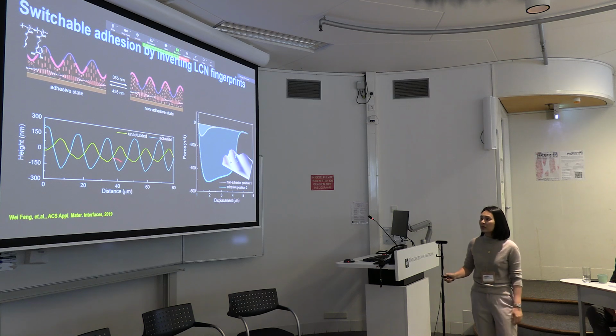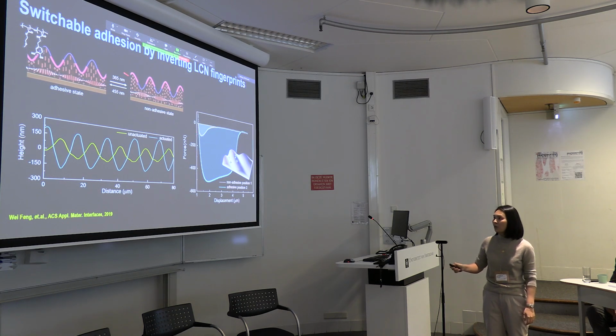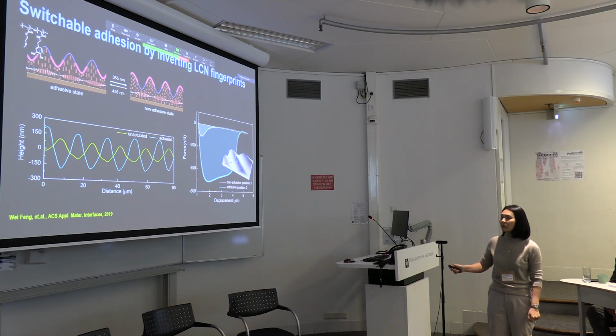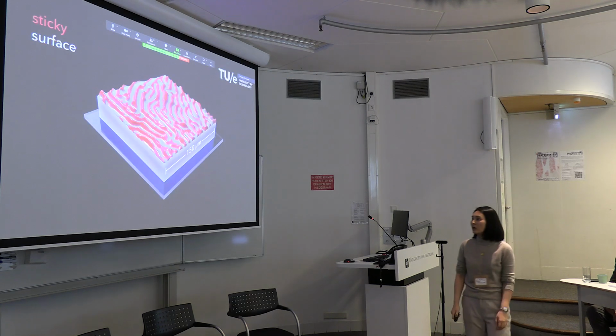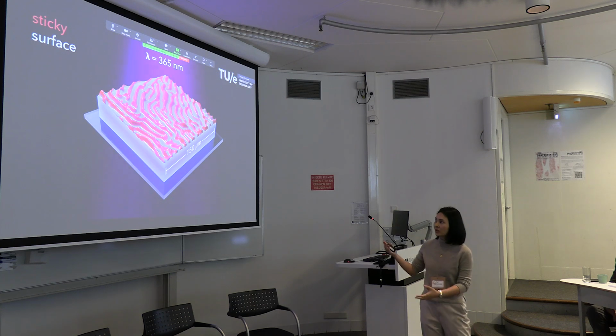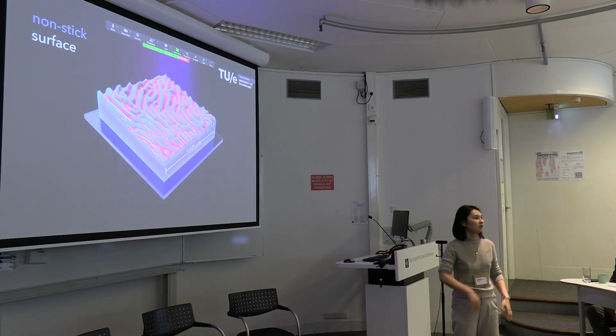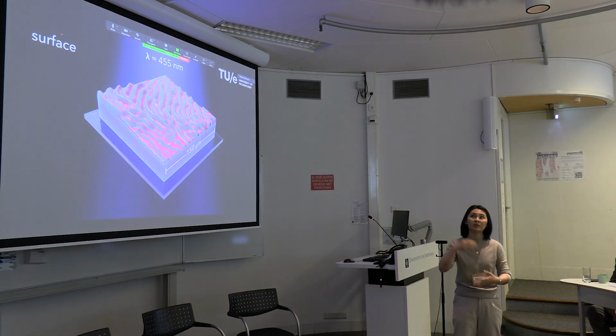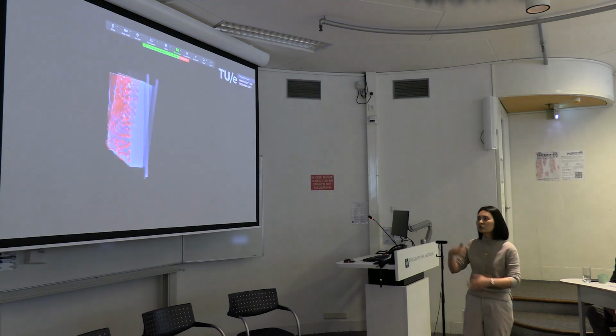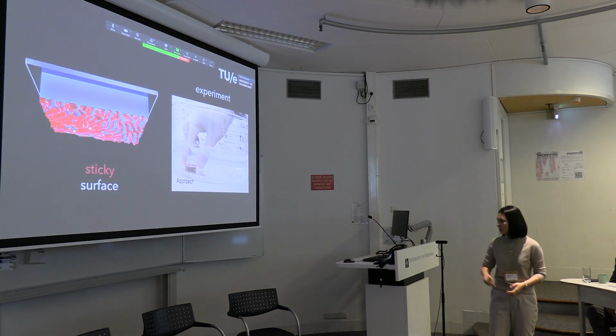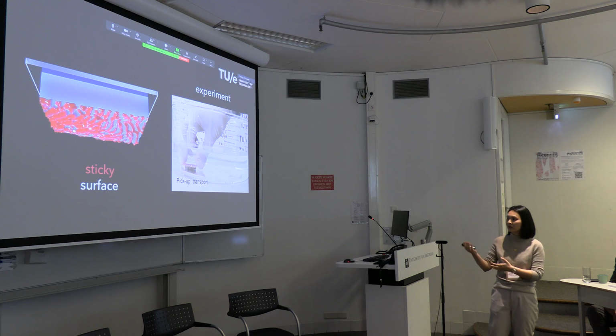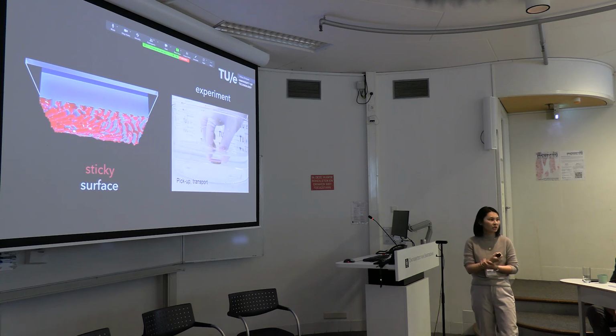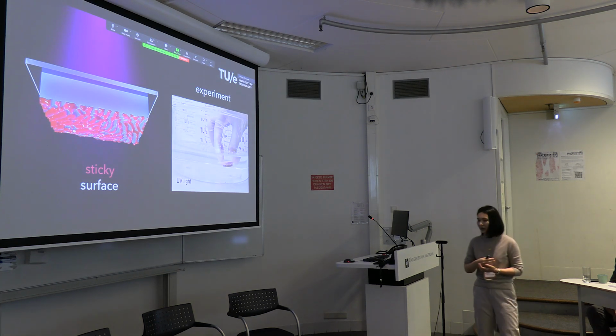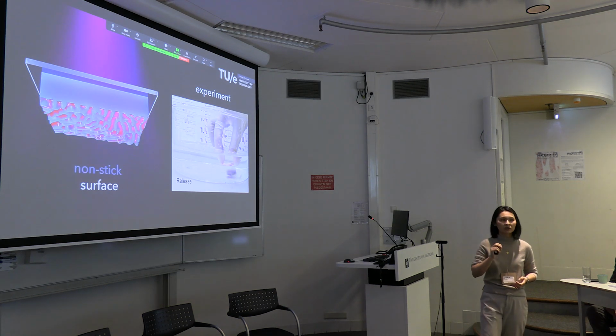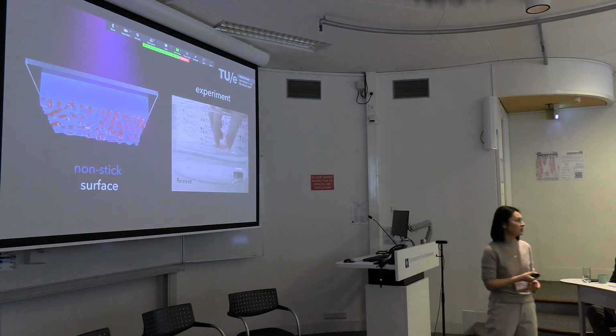Then when we measure this, the top, facing towards the air, has a much larger force than the bottom because there is no adhesive. What we are doing here is that our coating can start with an adhesive surface, and we switch, using light, electricity or whatever you like, to go to the non-adhesive state. In the adhesive state, we use this to grab an object, in this case in water. Then we can transport the object to the location we like. Then we switch on the light to go to the non-adhesive state, and we can release the object.